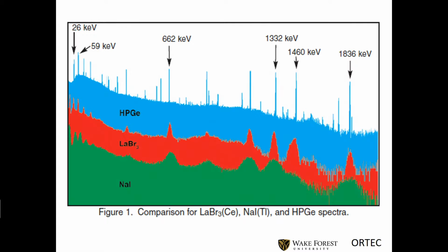Here's that standard sodium iodide, being used since 1949 and still used very widely, but you can just see, boy, that's miserable. And that's maybe $100 per cubic inch. And then here's one of the newer materials, lanthanum bromide. It's about $3,000 per cubic inch, and both of these are highly hygroscopic. Either one, set it on the shelf, it'll turn into a liquid puddle.